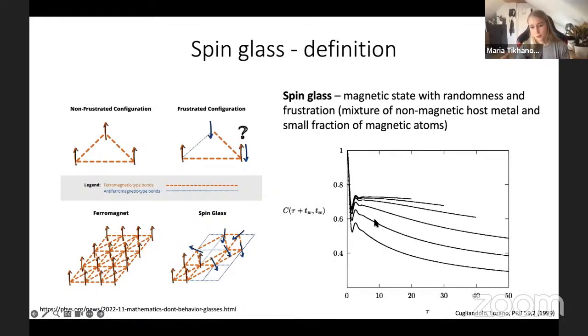Another way to look at them is to look at out of equilibrium dynamics of the systems. So imagine you initialize your system in some state, and then you wait for some time, and then you start measuring a correlation function. The C is essentially that, a 2-time correlation function. And what you actually see is that if you wait for long enough time, your correlation function starts saturating to some value, which means that you essentially break ergodicity. So your system does not explore the whole phase space, right? It just gets stuck in one of the minima, which I'm going to tell you a little more about. In these curves, if you don't wait for long enough time, then you don't reach that equilibrium state, so your correlation function slowly decays to zero.